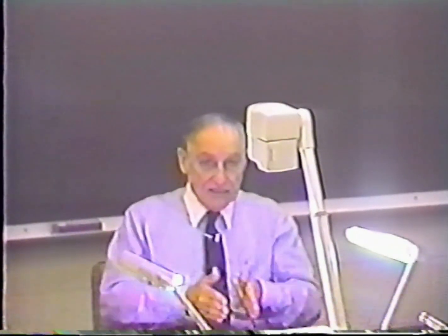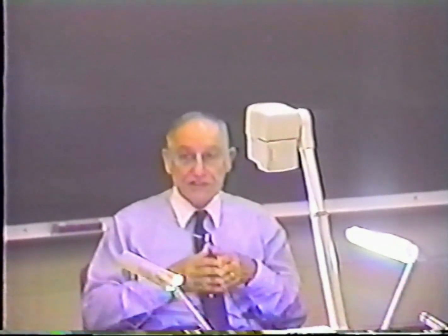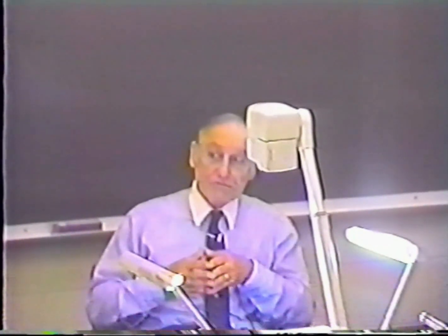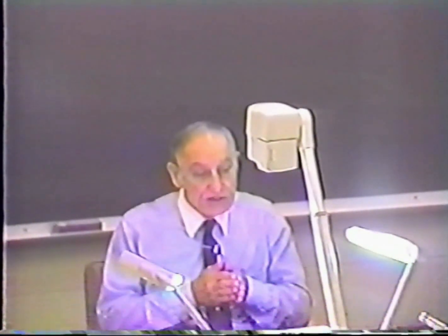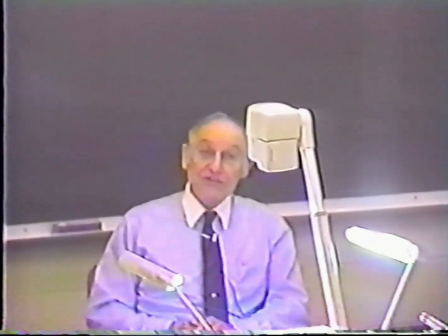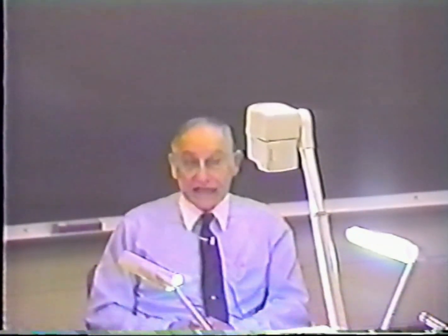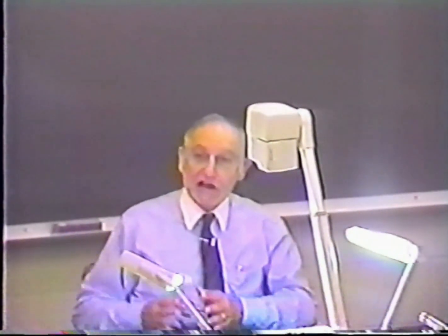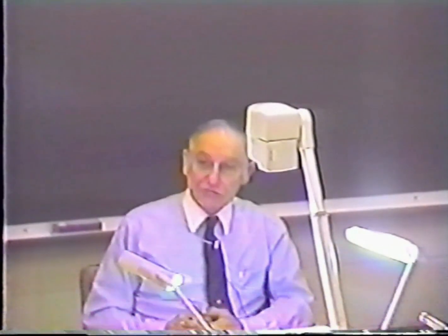Before you do any specification for a material using this method, you have to take the material constants with respect to the crystalline axes and do the transformations required to express them within the framework of how the actual crystal is oriented with respect to your structure geometry. So that's where that comes in, and that's a very good point because it tends to get pushed under the rug sometimes. Thank you for bringing it up.